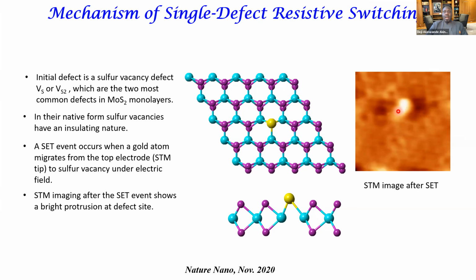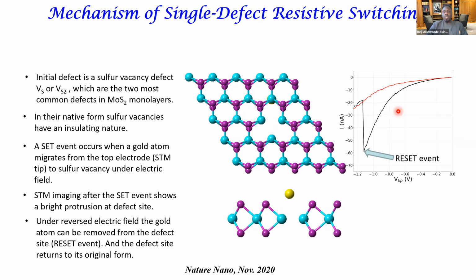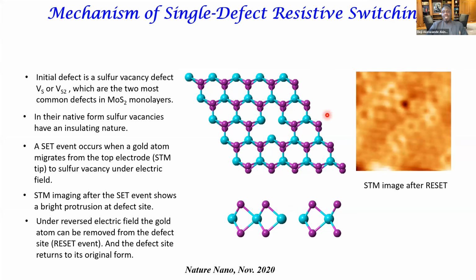Then it can apply the reverse voltage to turn it off or reset it. Around 1.1 negative voltage, it goes back to its initial state. The hypothesis then was that the gold will be debonded from that site. To prove it, he does imaging exactly after, and we can see that indeed the vacancy has recovered. The gold atom is no longer present in this vacancy.